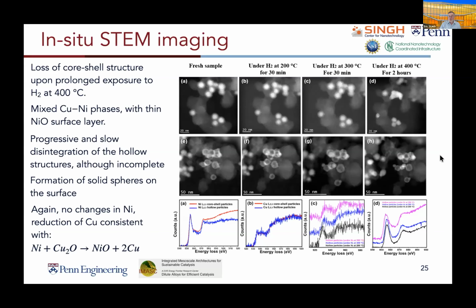Generally, what we will do is run the reaction condition for some extended period of time, like 30 minutes at 200 degrees C. We may image one area, but of course, we'll always go and look at other areas to see if there are changes that are different, right? If you see something different, then that indicates that there are strong electron beam effects.